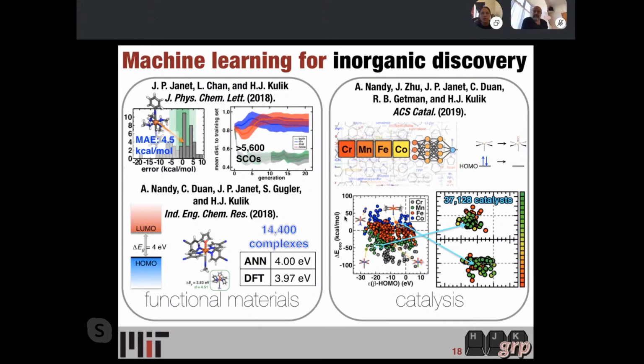For instance, on 10 molecules where we were targeting a band gap of around 4 eV, when we validated those results, we got a result that was around 3.97 eV. So we were able to control the error and go to new materials we hadn't seen before, but we're still keeping the errors not much above what the neural net training error was.